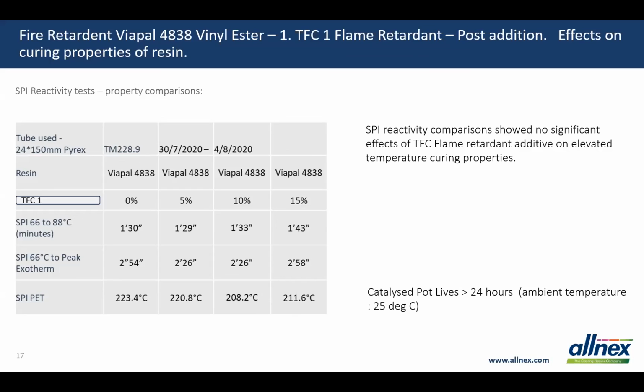It's a benefit in the fact that we are talking about elevated temperature curing. It's harder to achieve an inhibition effect compared to room temperature cured resin systems, but we were quite happy to see that we've got no such problems there.